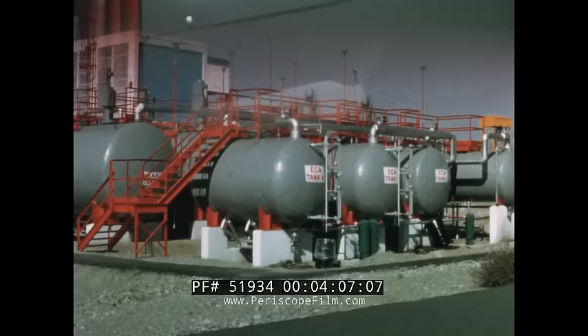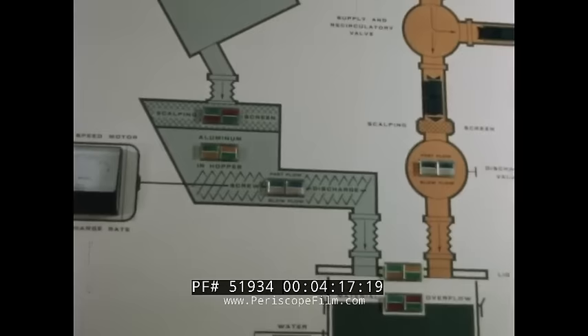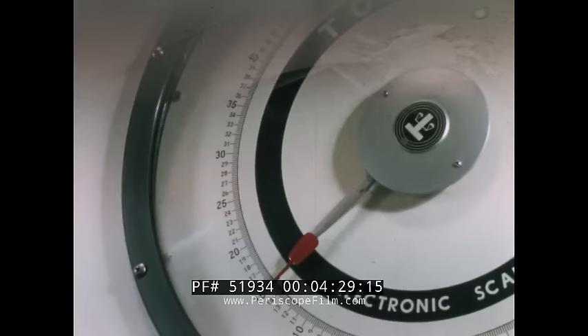Polymer, a binding agent, is fed from storage tanks through heat-traced pipes to maintain constant viscosity. The premix container receiving the polymer rests on a special load cell platform, programmed to measure only net weight. All feedings in the entire system are on a two-speed basis, fast and dribble. Load cells signal the feeder. A tolerance check for near perfection, then readout of weight and tank number from which it was drawn.